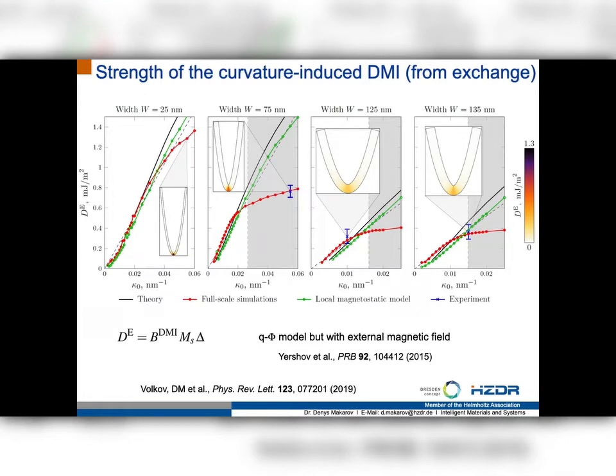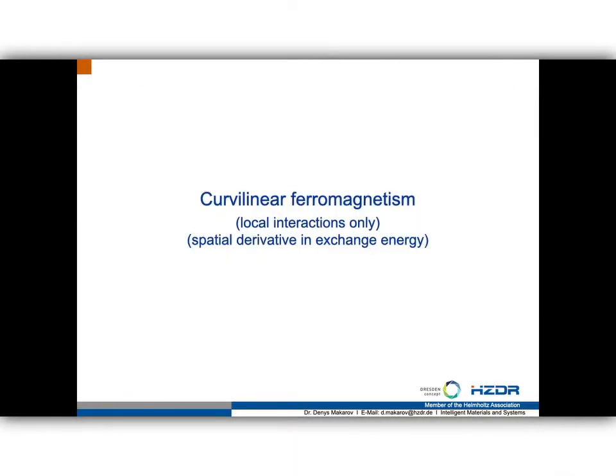And this is comparable to the well-optimized asymmetric cobalt-based sandwiches which you use, for example, in order to create Skyrmions or Skyrmion bubbles in such extended asymmetric cobalt sandwiches in films. This you can get in 10 nanometer thick permalloy, which is curved to geometrical parameters which are easily achievable in experiment. When you know that this effect of curvature-induced chiral interactions coming from the exchange are real experimental observables, you can of course think about which are striking demonstrations of these effects.